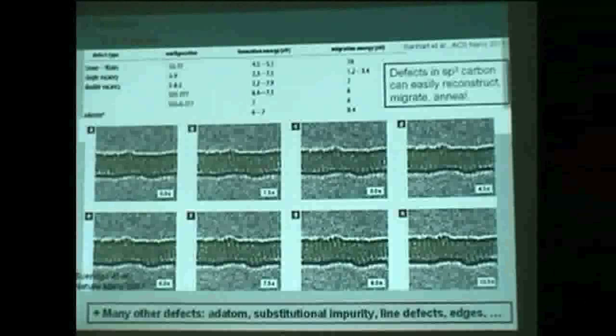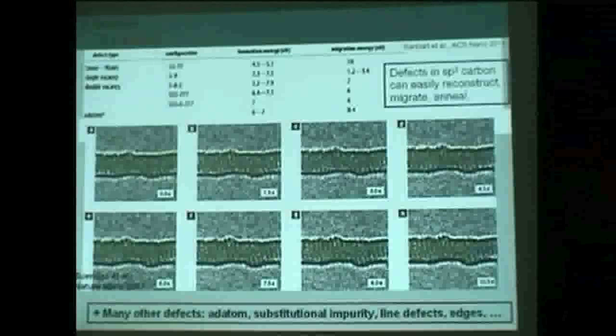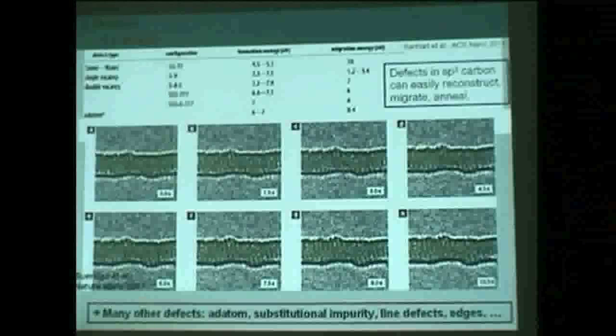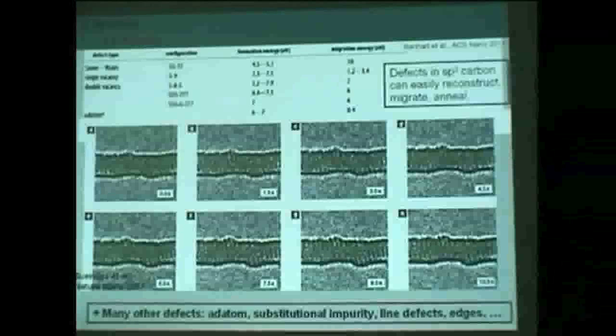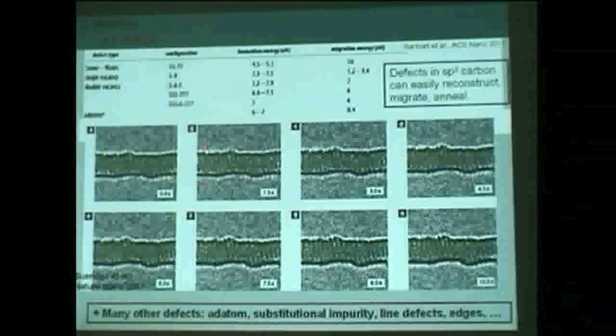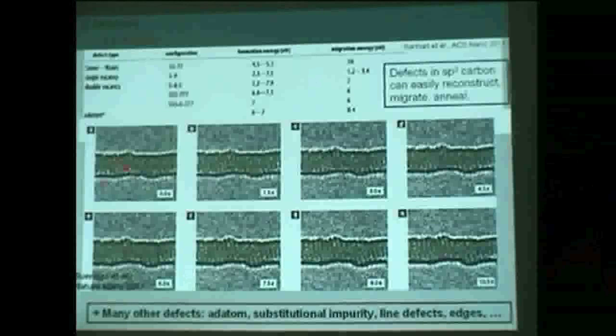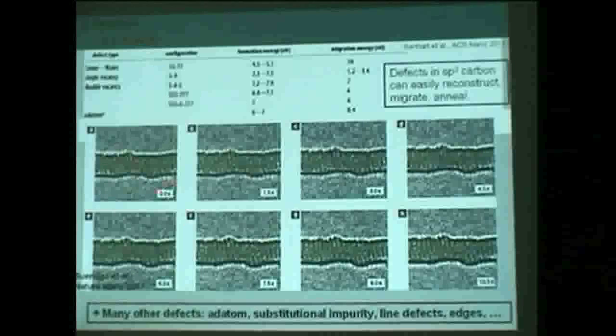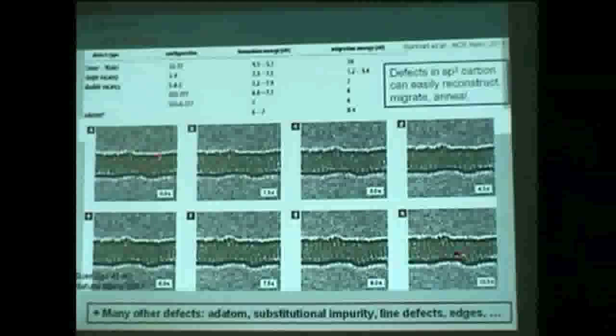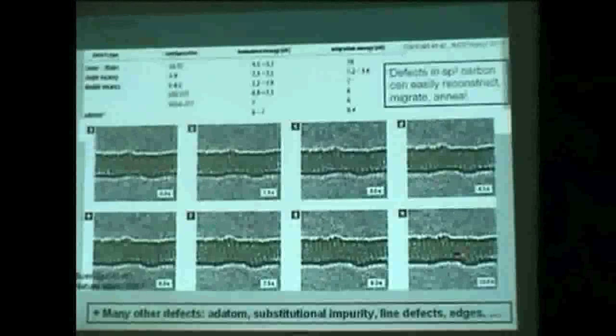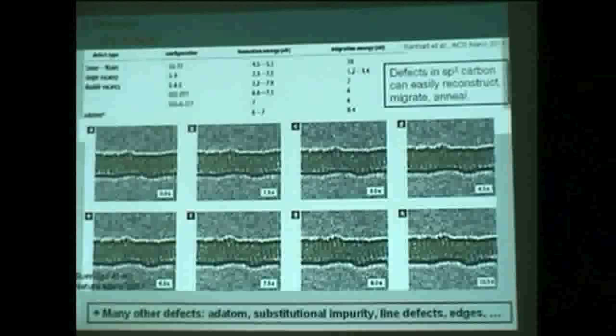Another thing is not just reconstruction, but also migration. Defects, like in any crystal, can migrate and move in the crystal if you have enough thermal energy, for instance. And this was observed experimentally. Here in blue are pentagons, in red are heptagons, and you see that as a function of time, the position of the pentagons and heptagons move. They do not stay at the same position. When you hit them, they start migrating. So you see this migration.